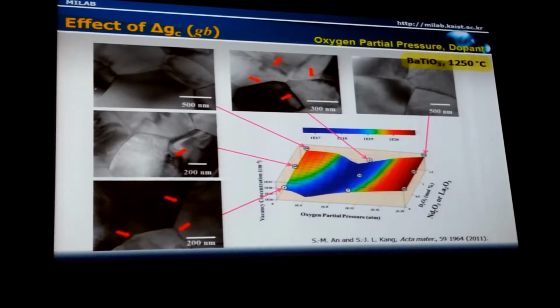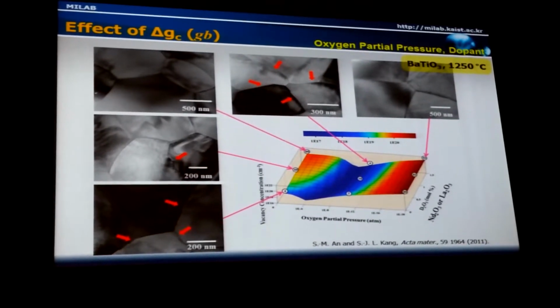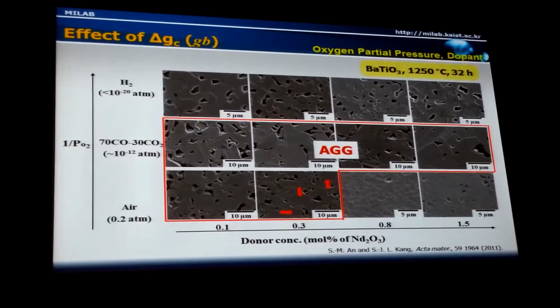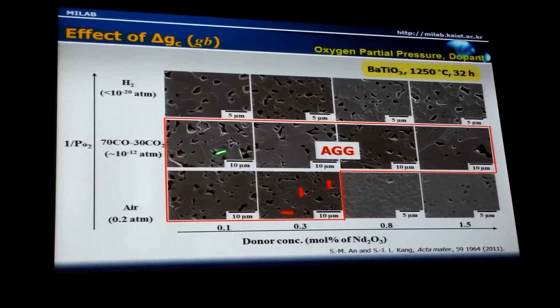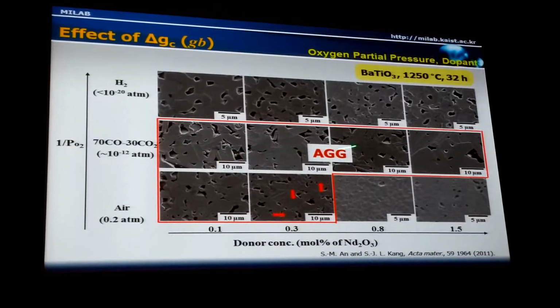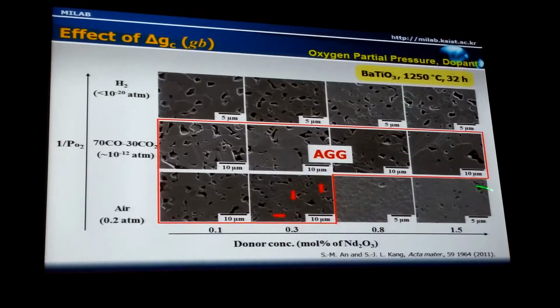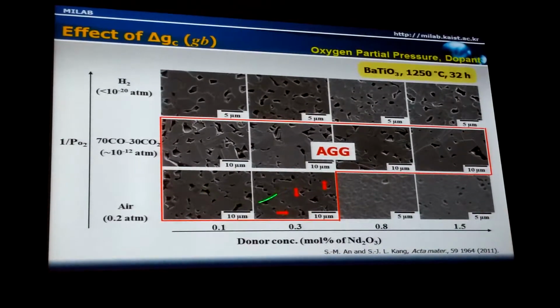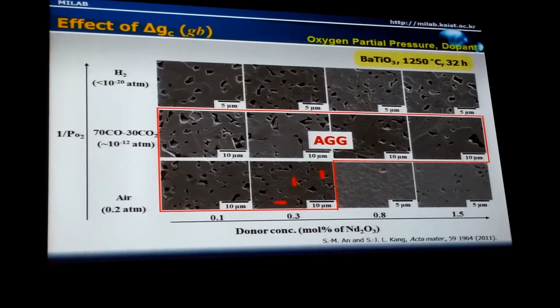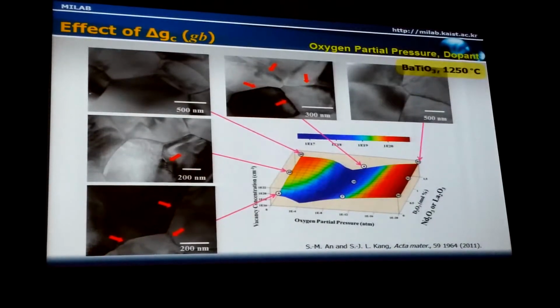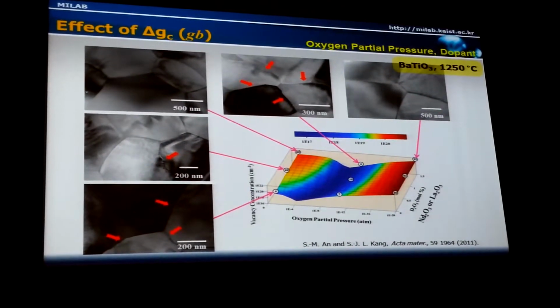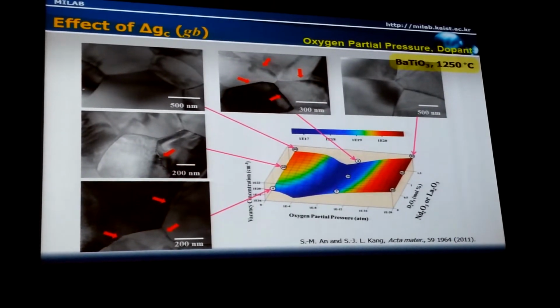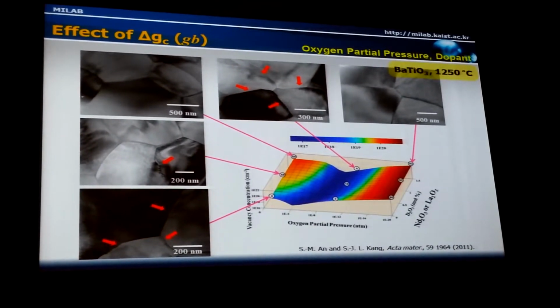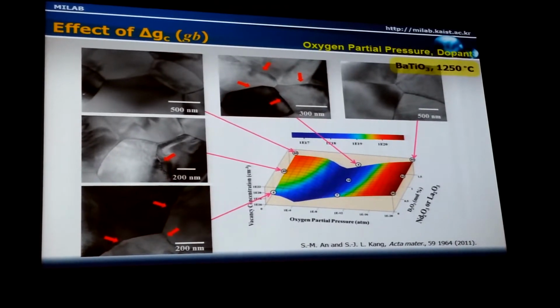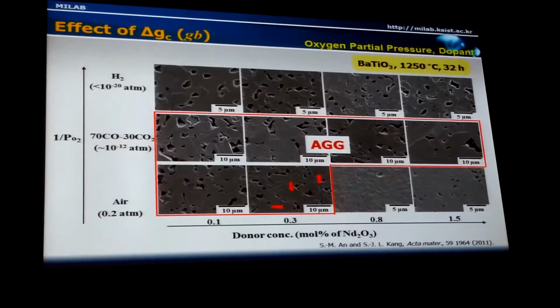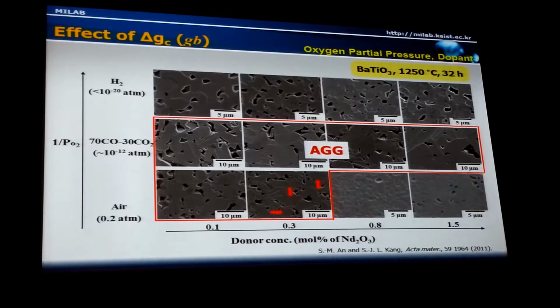So we prepared many samples under different experimental conditions and then observed the microstructure. Of course, there are many samples that exhibited abnormal grain growth and other samples, normal grain growth. When you compare the micrographs with the previous figure on grain boundary structure and total vacancy concentration, we can easily notice that abnormal grain growth occurred in the samples with faceted boundaries, and normal grain growth occurred in samples with round boundaries.